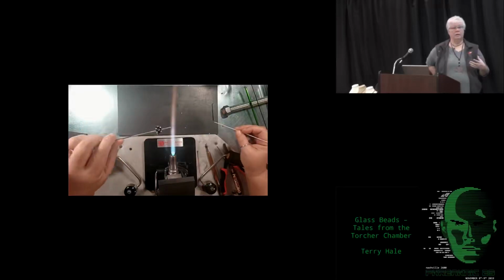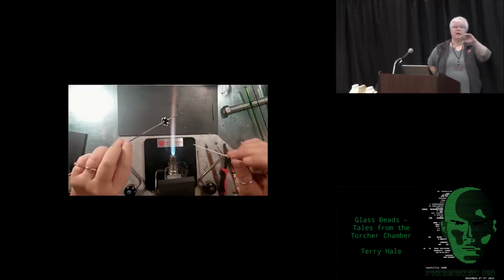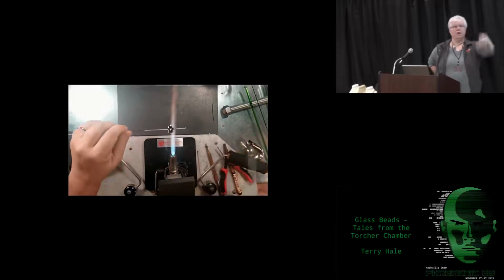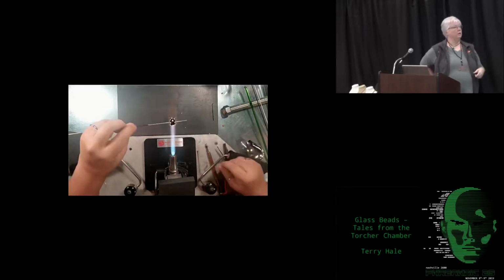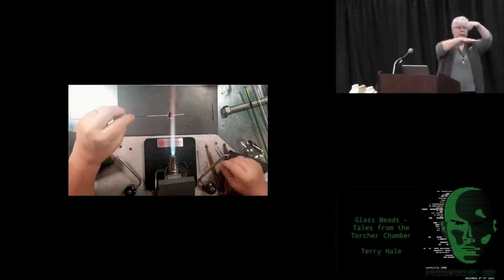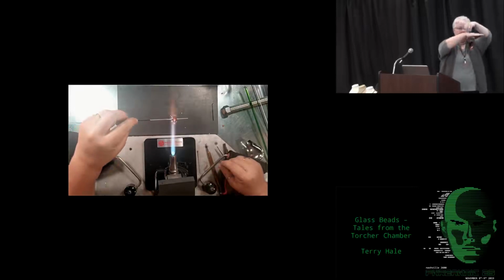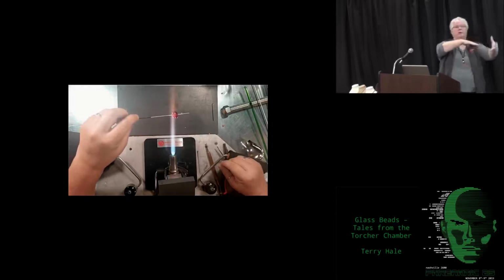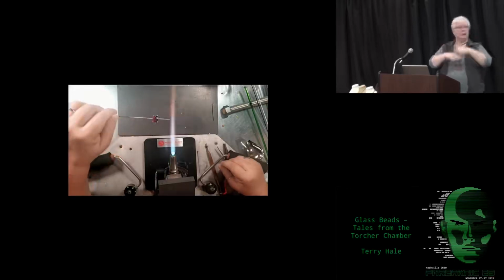Are you spinning it a lot faster than normal with the dots? I am, now because I'm trying to heat the little dots and I'm trying to get the heat to do the same all the way around pretty quickly. And when you first put the dots on, they tippy toe, they stand up like this, and what I want to do is heat them enough that they spread out, make a dome, because if they're tippy toe up on the end of the ball, if you bump it, they'll fall off. So you want as much of that area touching the base as possible.